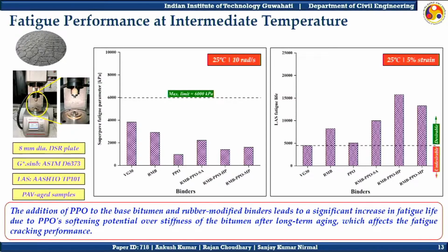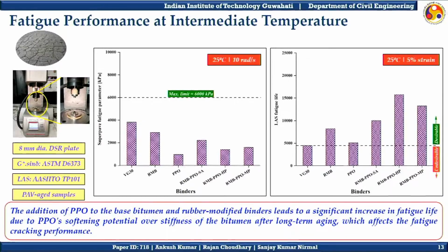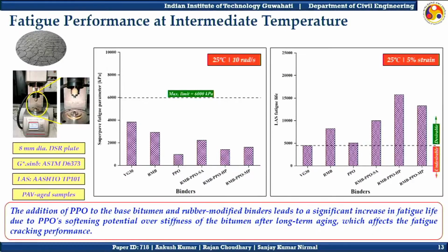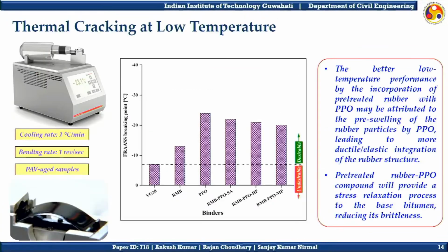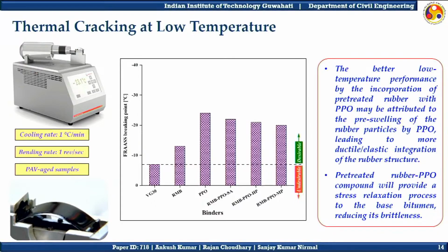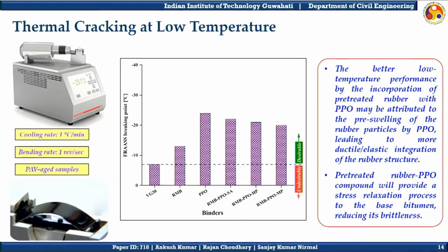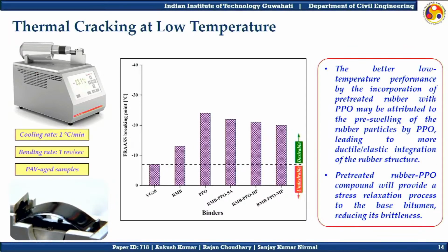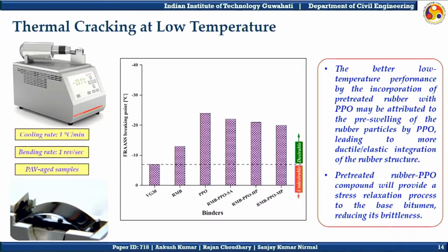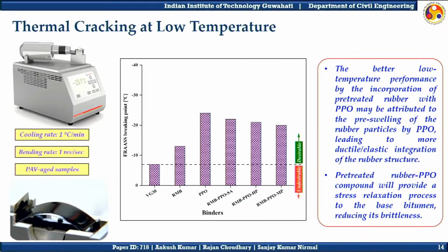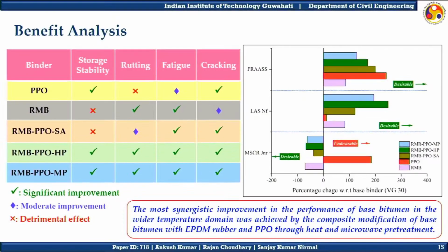So in terms of fatigue performance, the fatigue parameter and LAS fatigue life were conducted, and as we can see here also, for the composite rubberized binder with heat pretreatment, the fatigue parameter increased significantly, by around 250%. Coming to thermal cracking, the Fraass breaking point was conducted, and as you can see here, the PPO has the highest Fraass breaking point because of the softening effect it imparts to the base binder, while the composite rubberized binders also had a Fraass breaking point comparable to the PPO. So coming to the benefit analysis, majorly four parameters were important for different modified binders.